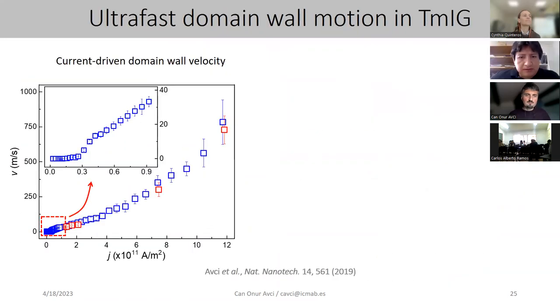So in the case of the thulium iron garnet, we did not try because the temperature, I think, is 1.5 Kelvin. So it's not a good system to study that. The best systems to study the effect of compensation temperature on domain wall velocity are basically terbium iron garnet, gadolinium iron garnet, europium iron garnet, where the compensation temperature is floating around 200, 250 Kelvin. So those are more accessible temperatures in terms of measurements. But currently we are still working on an upgrade of our system, so I cannot tell. Maybe 1 year from now I can tell you something more, but right now it's a work in progress.